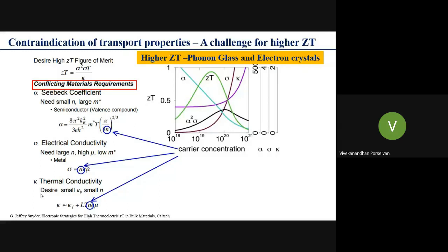we should have a very, very lower lattice thermal conductivity, and a very, very lower carrier concentration. If you look at the desirables, they are quite contradictory. Thereby, it is very challenging to achieve higher efficiency, in other words, a higher ZT in the thermoelectric material.